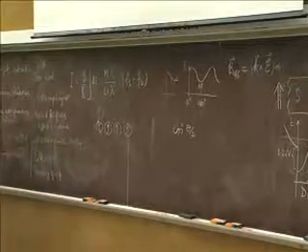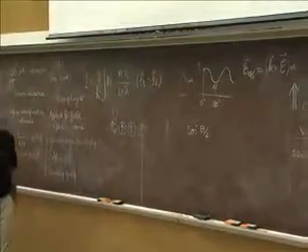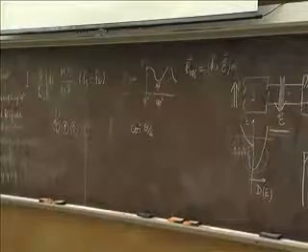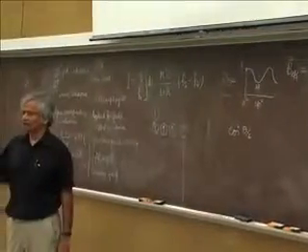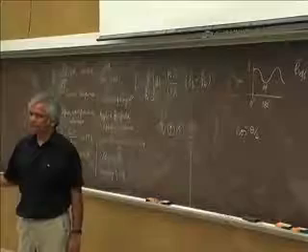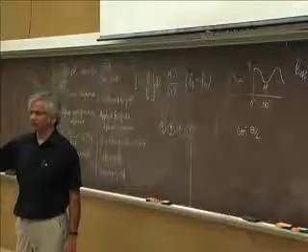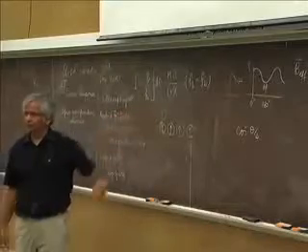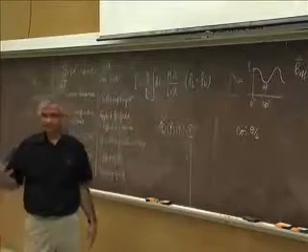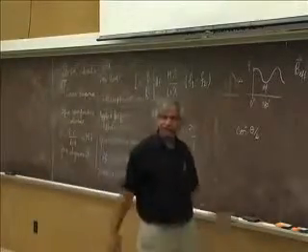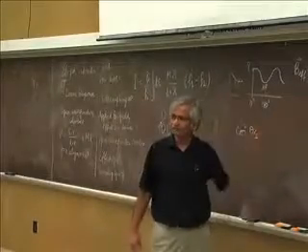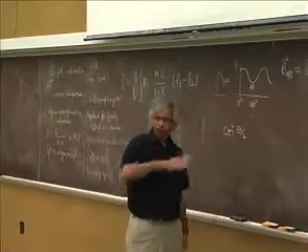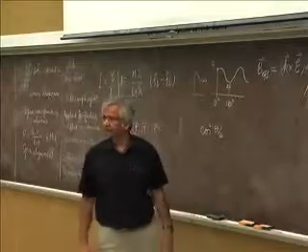Now, the spin orbit coupling, as I said, is variable in different materials. In silicon, it's much smaller than in gallium arsenide, which is smaller than in indium arsenide. Indium arsenide is the one that was used for many of these experiments. So if you're looking for strong spin-orbit coupling, that's where you usually go, indium arsenide. If you're trying to avoid it, then silicon is usually a good play.